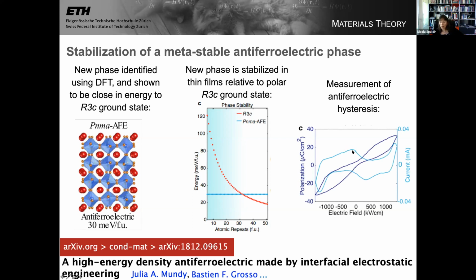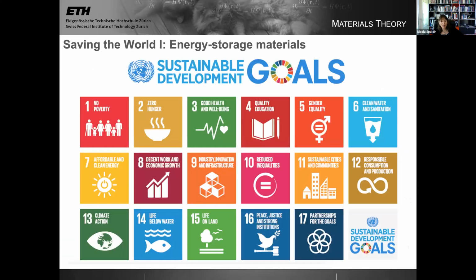It has what's called anti-ferroelectric hysteresis. Look at the blue lines here. So in the absence of any electric field, the measured polarization is 0. But when you apply an electric field, it switches to a polar state. You take the field away, it switches back to this non-polar state, and again in the other direction. And these antiferroelectric materials are very important because they're candidates for very high energy storage. So this is my first example of a density functional theory calculation being used to engineer materials that might contribute to saving the world in terms of affordable energy and climate action, because one needs, of course, if one has an alternative source for energy, to have a way to store it, and antiferroelectrics are candidates for this.